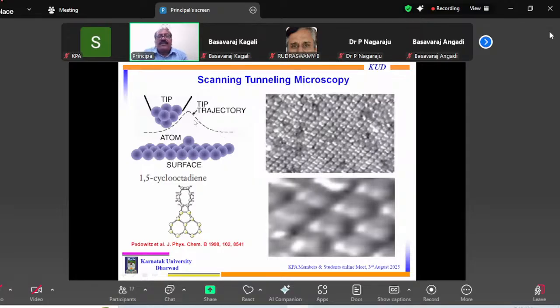This is how this technique of deposition has been studied by others. Scanning tunneling microscopy: I don't have to tell how it works, because you have the scanning probe, with just one atom sitting at the end, one atom from the surface. It will measure the tunneling current, and finally it will construct an atomic resolution image of a surface. So a bare silicon looks like this, and 1,5-cyclooctadiene is a molecule that, as the ENE indicates, has a double bond. Once this molecule gets deposited, you can see this surface changes to this, and literally each bump is nothing but a molecule deposited on it.